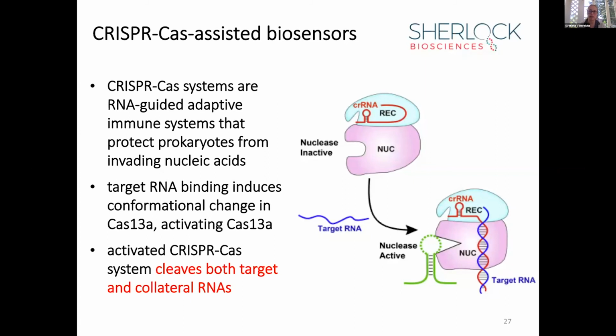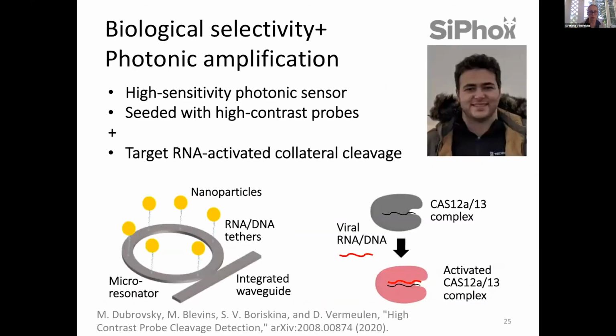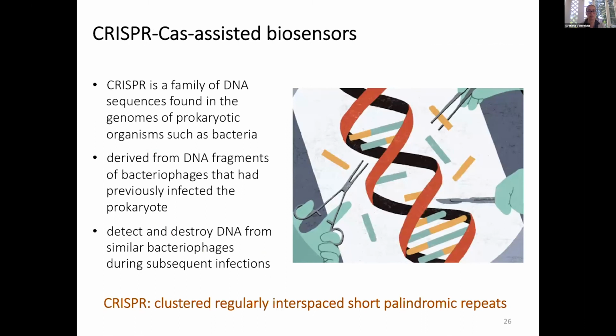So it's like collateral cleavage, which does not need to be the same RNA as present in the virus. And so going back to our situation, in this case it will also cut these RNA strands that attach our probes to the detector. And it means that even if you activate one complex, and you can get this complex in close proximity of the sensor, it may actually cut thousands of probes. And it would be enough to have just one viral particle to get it activated. So that's where the amplification step comes from.